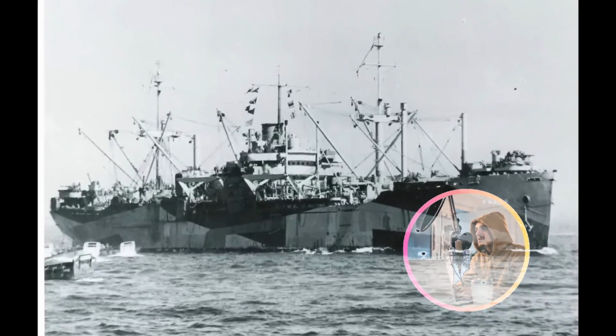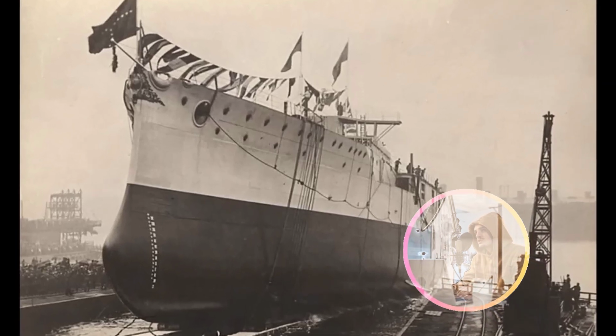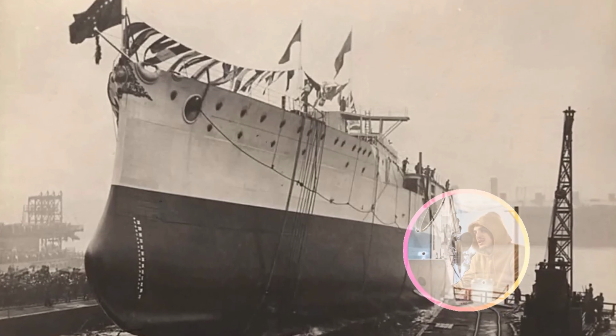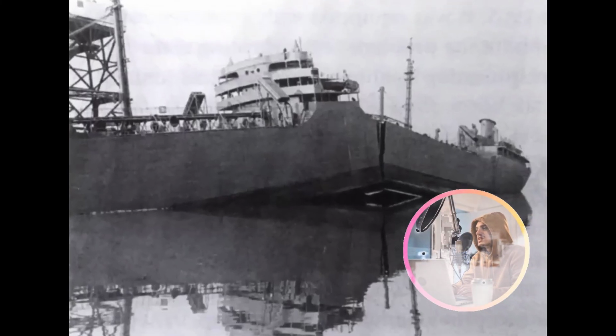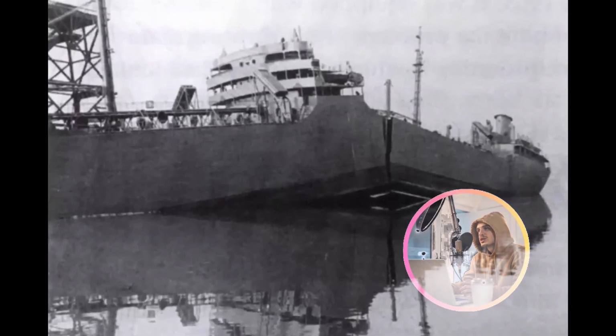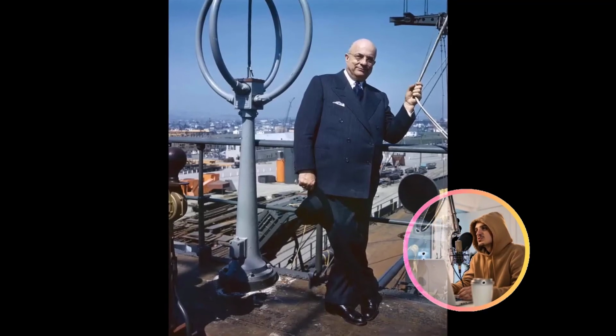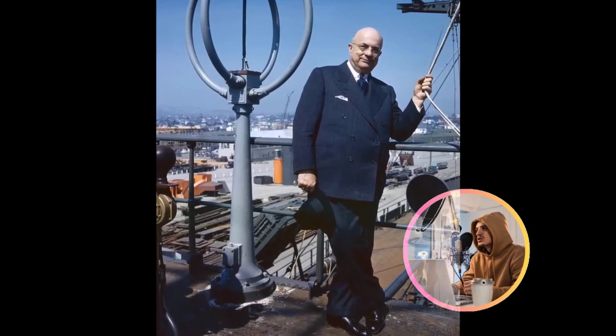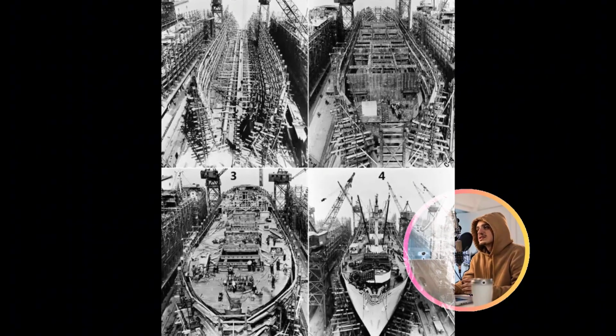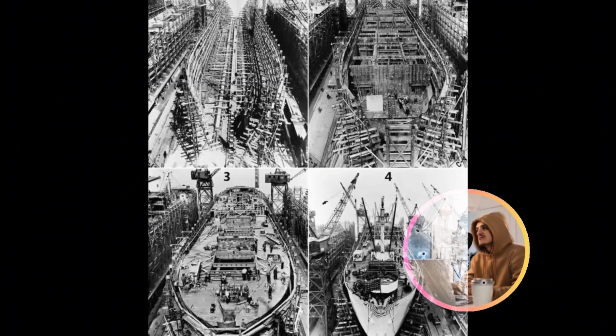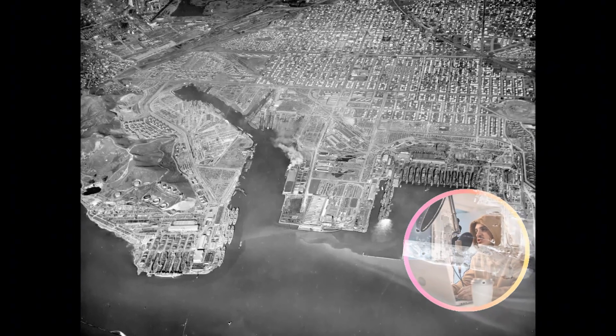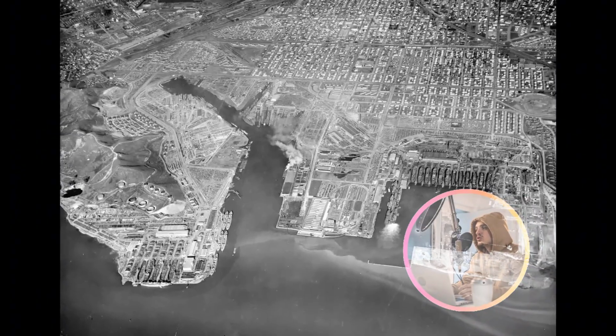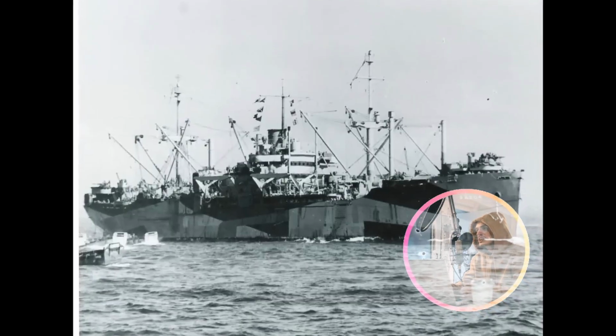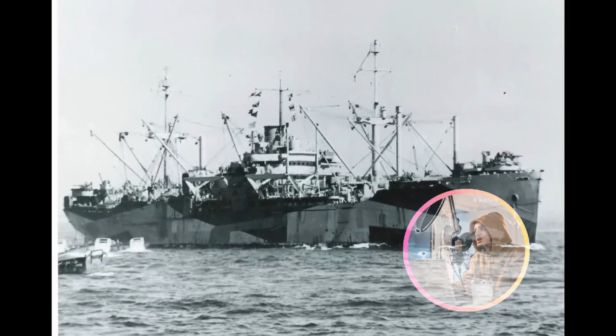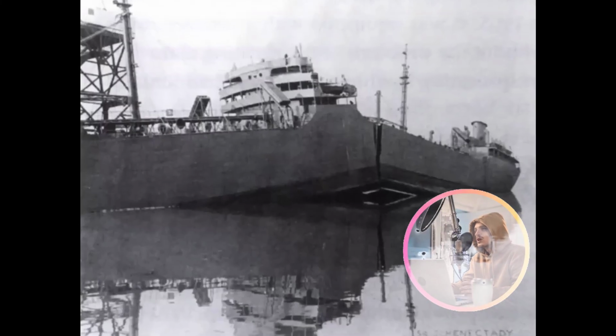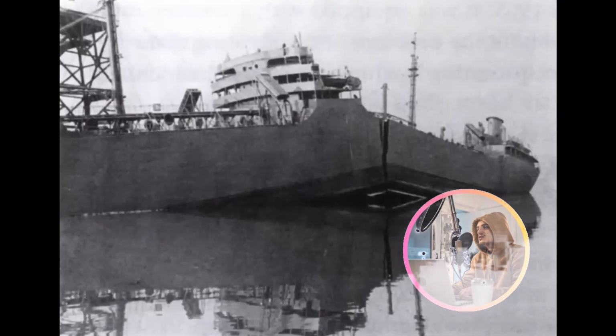Quality control ascended to an almost obsessive level of scrutiny. Every completed weld underwent meticulous magnetic particle inspection, a sophisticated technique where finely dispersed iron powder, under the influence of magnetic fields, revealed microscopic cracks that were utterly invisible to the naked eye. Further, ultrasonic testing was employed to thoroughly check internal weld quality, guaranteeing full penetration and the complete absence of hidden voids or imperfections. X-ray inspection provided an even deeper level of analysis for critical structural welds, generating permanent photographic records that meticulously documented the integrity of each weld. Crucially, no ship was permitted to be launched until inspectors had unequivocally certified that every single weld met the exacting specifications.